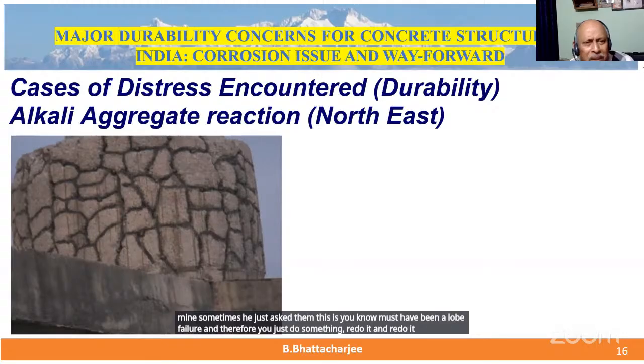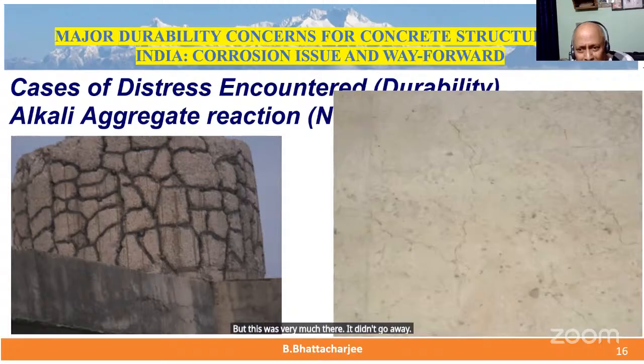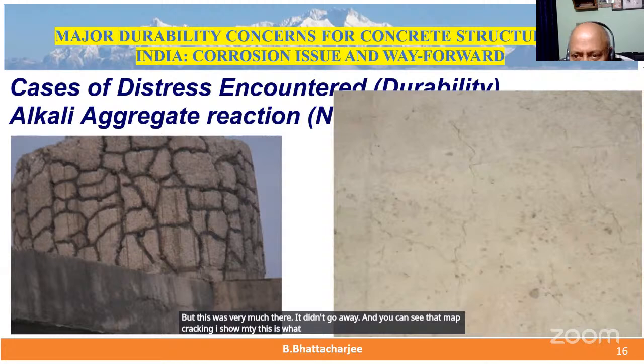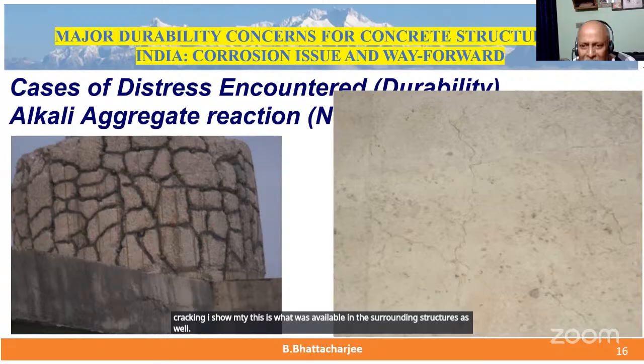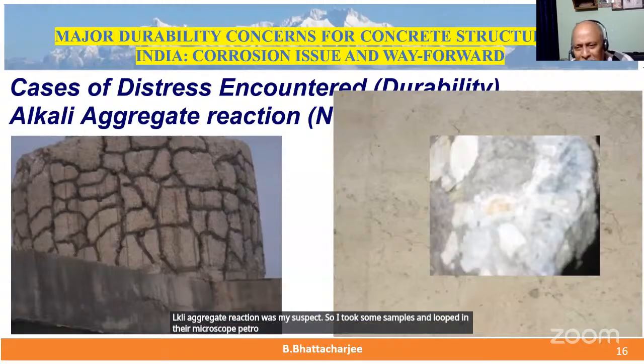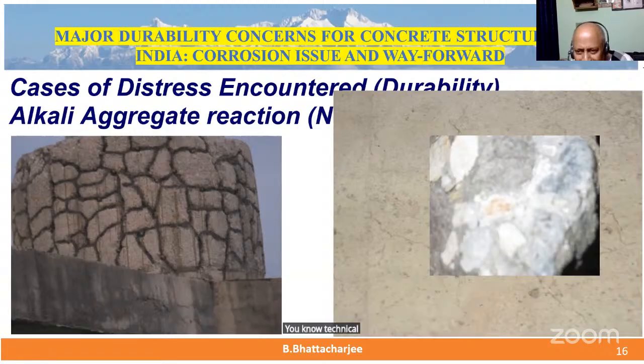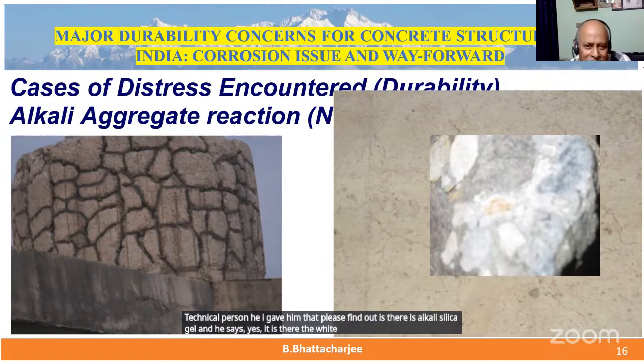Not redo it; epoxy or something was suggested. But this was very much there, it didn't go away. And you can see that map cracking I show, M-type, this is what was available in the surrounding structures as well. Alkali aggregate reaction was my suspect. So I took some samples and looked in a microscope petrographically. My geology colleague in the lab, technical person, I gave him that, please find out is there alkali silica gel, and he says yes, it is there, the white color alkali silica gel.